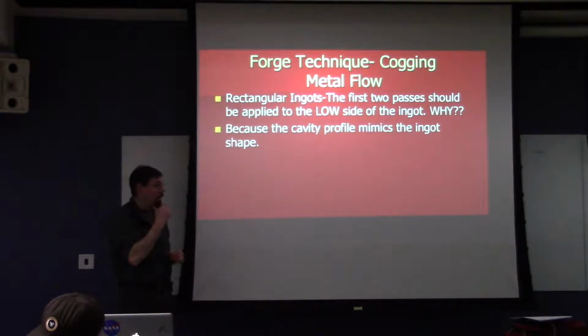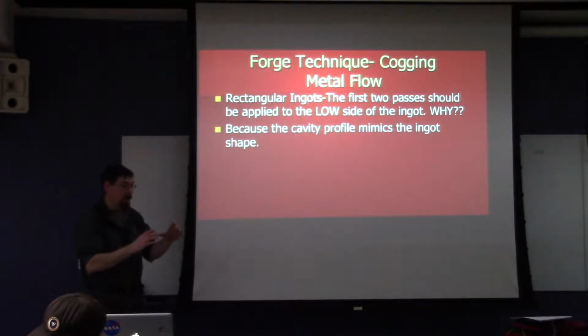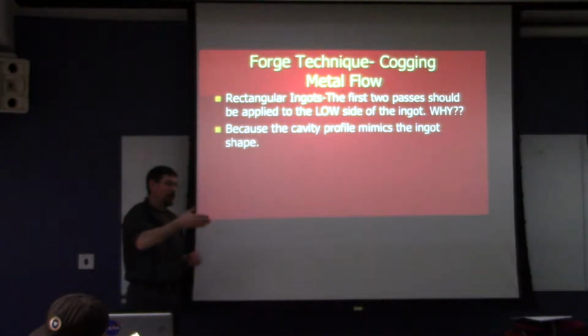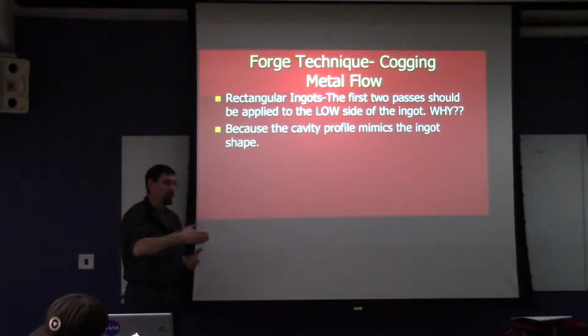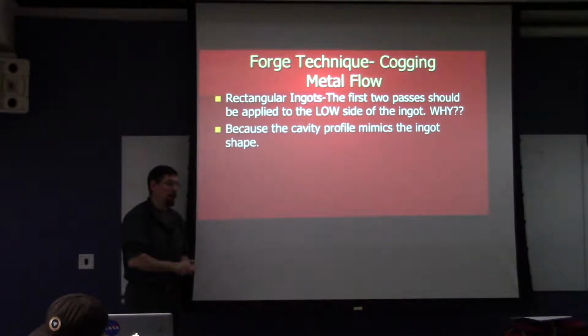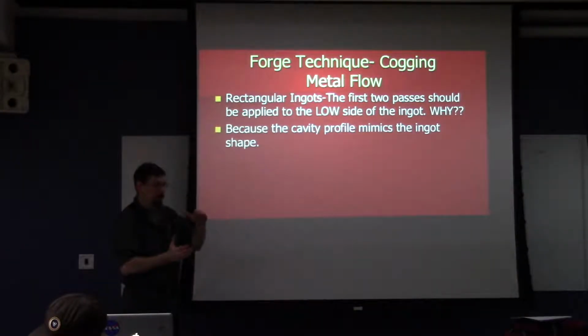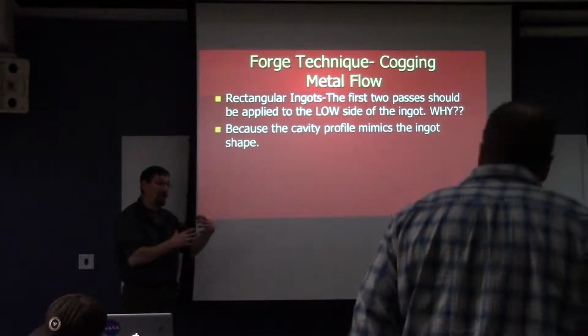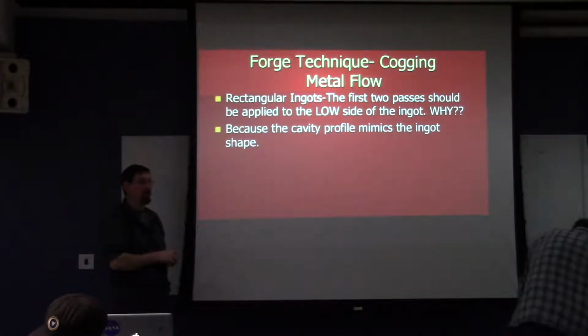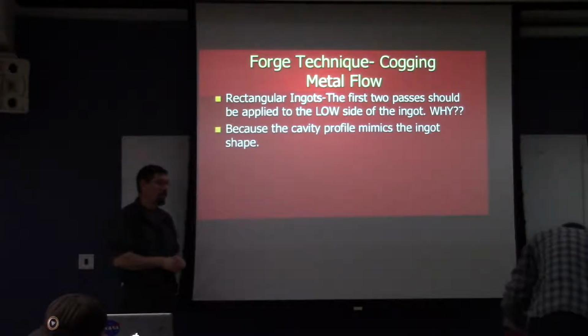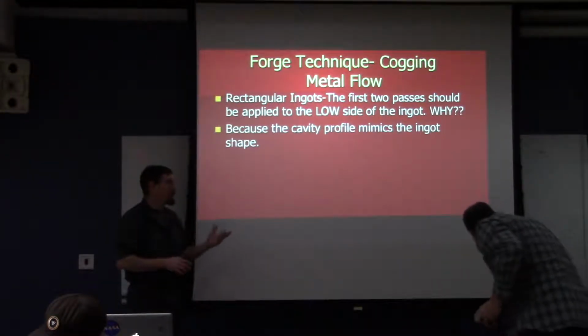So you can imagine if I took that rectangle and I stood it up so that the long edge is vertical, and I push on that, I'm going to have the ellipse wanting to get shorter and fatter. I kind of showed that in the upsetting experiment that was done, where they had the holes drilled down the little blocks and they upset. The same thing happens in a rectangular ingot.